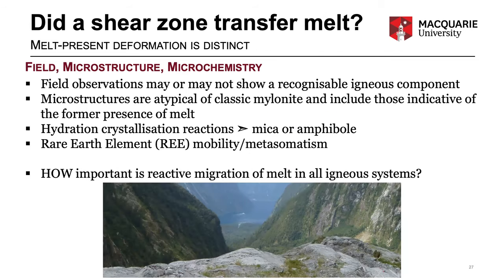So to summarise, the field observations of shear zones rich in leucosome lenses and dikes are commonly used to infer melt-present deformation and a former melt transfer zone through the crust. However, in our case study of the Fiordland lower arc crust, we found little field evidence along these lines. We therefore had to rely on the microstructures.